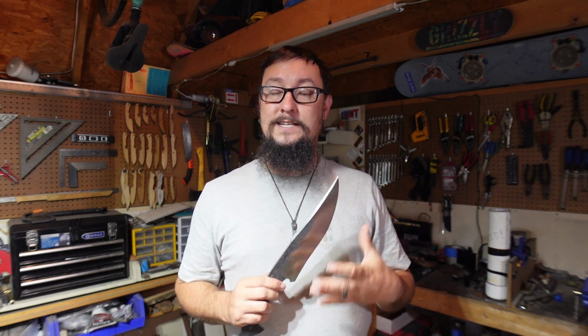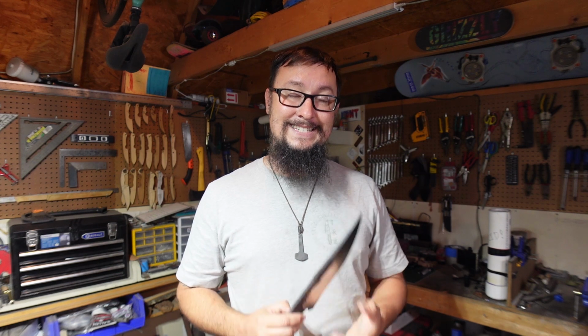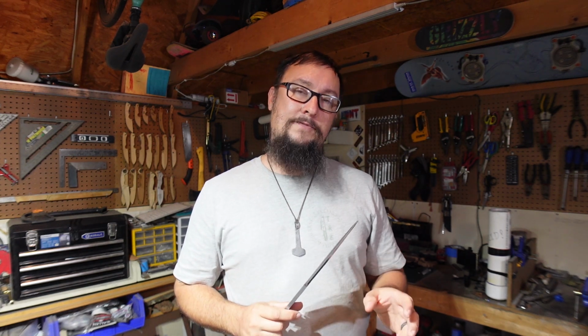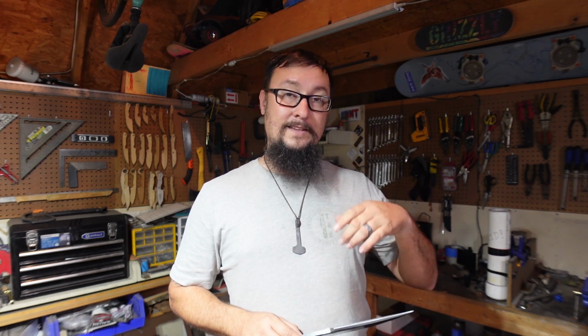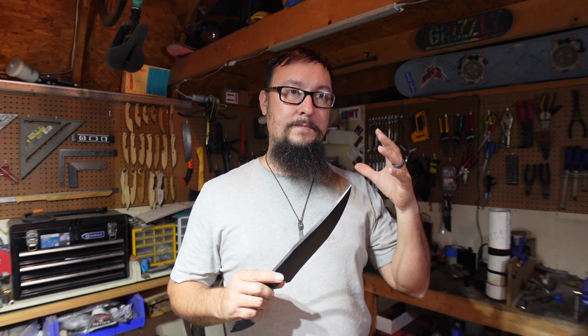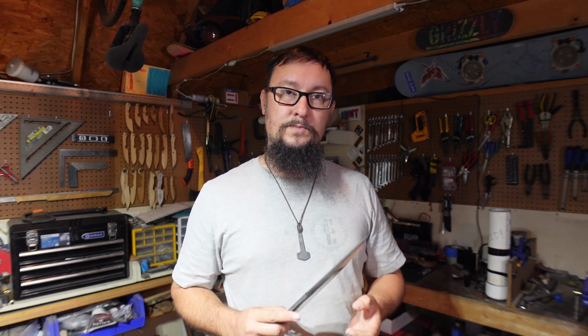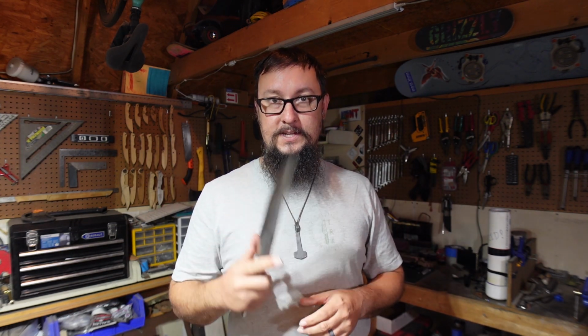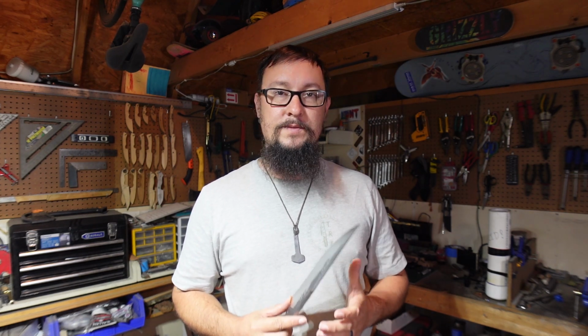I've done videos in the past where I talk about the fact that 5160 is probably one of the most forgiving steels to heat treat with a backyard method, to where you don't really have to worry about much. I have done the heat treat process all the way from quenching at 1475 degrees all the way up to 1650, so you can get a relatively hardened blade. You can get something that is usable in a wide range of heat treat processes with this particular steel. Like I said, it is probably one of the most forgiving steels that you could possibly heat treat.